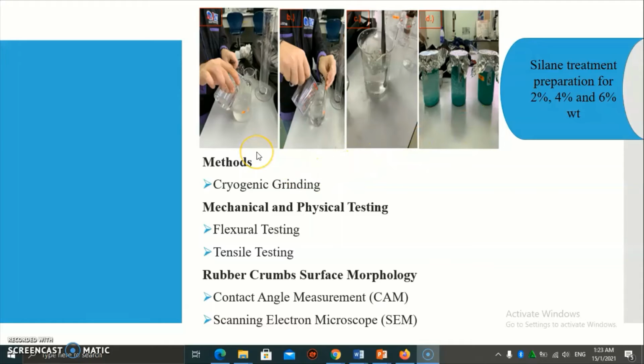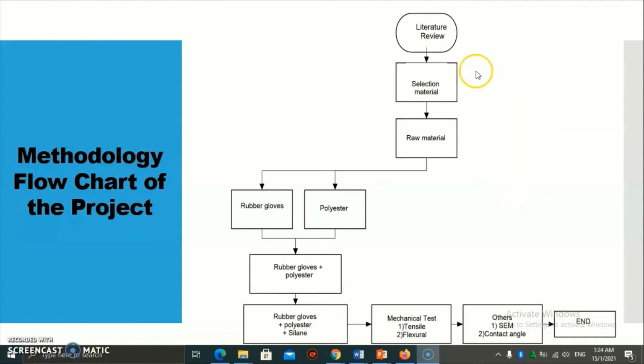The method that we use is the cryogenic grinding process. This cryogenic process cuts the rubber glove into smaller pieces, which is called rubber crumb. For the mechanical and physical testing in our project, we use flexural testing and tensile testing. For the rubber crumb surface methodology, we use contact angle measurement and scanning electron microscope. This is my methodology flowchart of the project.